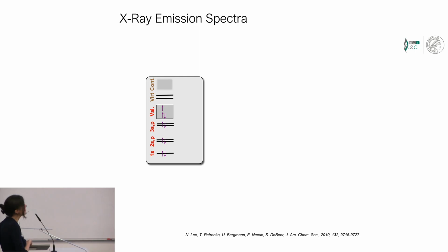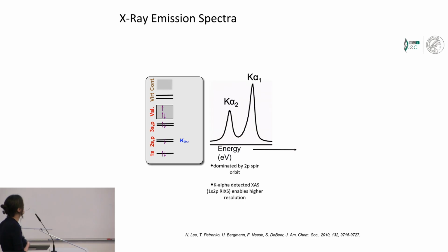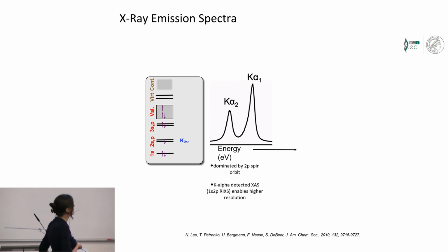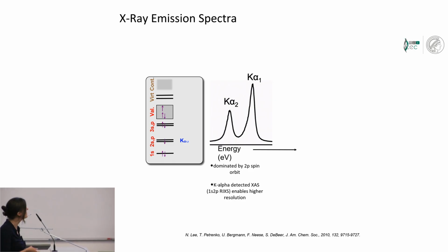As we already said, we can eject a 1s electron to the continuum. The 2p falls down and produces a fluorescent photon. This is what we refer to as the K-alpha line. If we have enough resolution in our spectrometer, we have K-alpha 1 and K-alpha 2 lines. Those are basically split by the 2p spin orbit in the final state, so into 2p 3/2 and 2p 1/2. This is actually something that chemically isn't that informative. It largely is dominated by spin orbit, but I will show you a bit later how this enables higher resolution experiments.